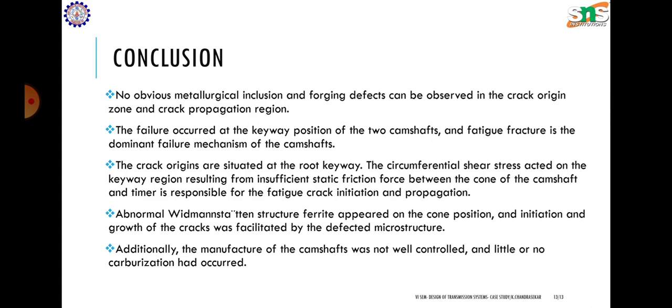Then the circumferential shear stress acted on the keyway region, resulting from insufficient static friction force between the cone of the camshaft and the timer. So this is responsible for fatigue crack initiation and propagation.